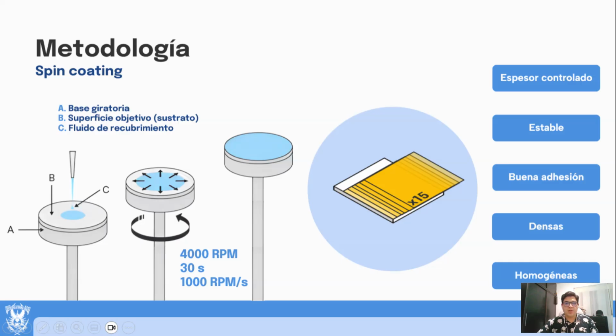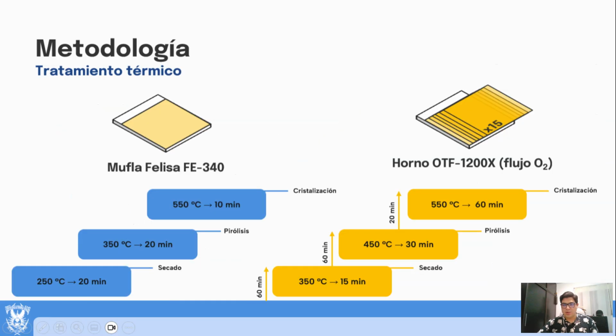Immediately after deposition, films undergo thermal treatment, pre-annealing, at 250 degrees Celsius on a muffle furnace, to evaporate residual solvents and decompose organic nitrates, followed by final annealing at 550 degrees Celsius for 1 hour in a tube furnace with oxygen flow system to crystallize the perovskite phase. This step is critical, as insufficient temperatures may leave the film amorphous, while excessive temperatures can promote bismuth volatilization and